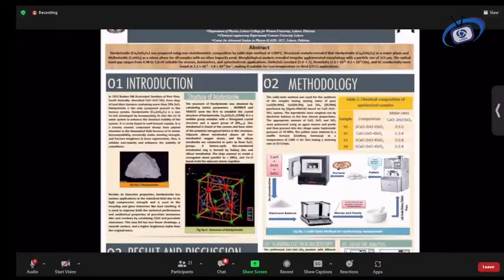So the structure of Hardystonite was obtained by calculating lattice parameters. It had a tetragonal structure and P421 space group. In this structure, a heterocyclic five-member tetrahedral ring is formed by linked zinc silicon tetrahedra. The rings are connected to create a conjoined sheet parallel to C001, and calcium oxide bonds hold the adjacent sheets together. So for the methodology of my research, for synthesizing Hardystonite, I used the solid state method,